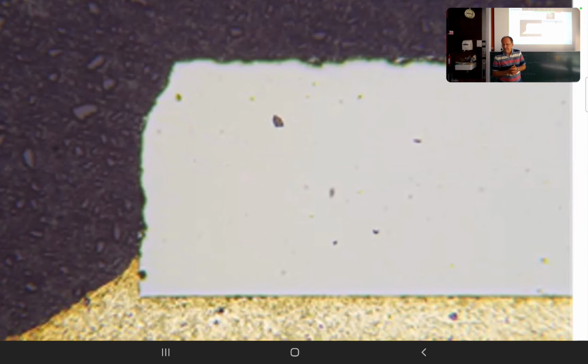I got that, and it really looked like a plastic device. I gave it to my lab. They wanted to cut it, and here we already had a problem, because cutting it in half was really a problem. And when we managed, of course, we saw it's not a plastic package; it's a ceramic package. So here you see something similar to aluminum oxide, but it's dark. The material here is just for embedding. That has nothing to do with assembly and packaging.